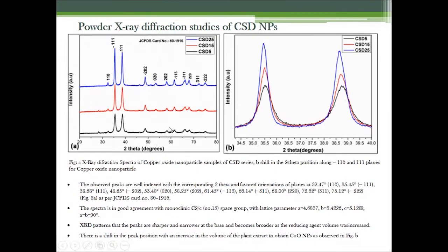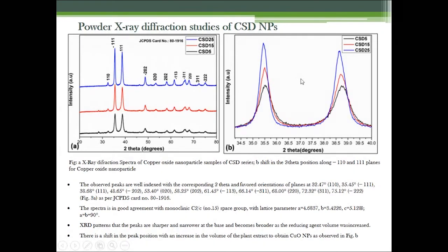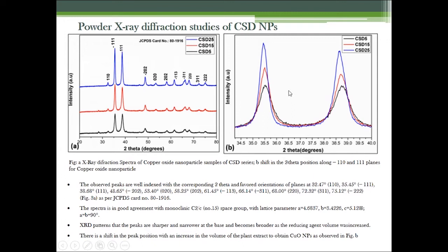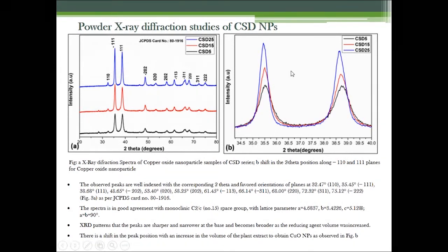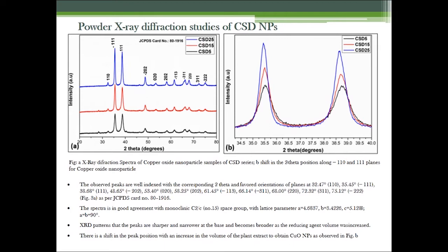It is evident from the XRD patterns that the peaks are sharper and narrower at the base. In this second image, we will be able to observe the peaks are sharper and narrower at the base and become broader as the reducing agent volume was increased. There is a shift in the peak position. You may observe here there is a slight shift in the peak position with an increase in the volume of the plant extract used to obtain the copper oxide nanoparticles.